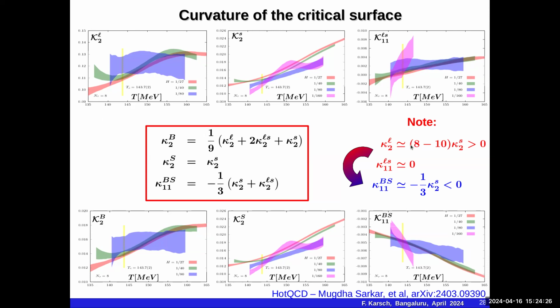What one learns here, for instance, is that the curvature coefficient in strangeness flavor chemical potential direction, which you see here, is about an order of magnitude smaller than the curvature in the light quark chemical potential direction. However, when you go to the baryon and strangeness basis, then the curvature coefficients in both directions are quite similar.